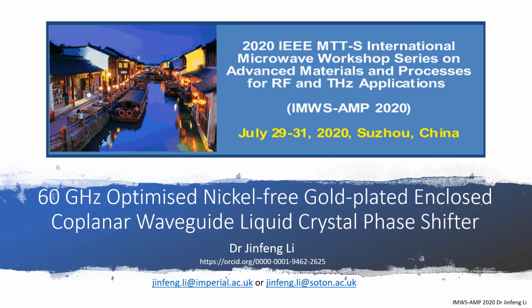In conclusion, this work numerically investigates and experimentally optimizes a novel nickel-free gold-plated ECPW LC phase shifter at 60 GHz. By comparative analysis of adaptive meshing inside metals versus the surface impedance models without meshing inside, we derived the threshold at which the conventional surface impedance model is invalid. This can be extended to a wide range of millimeter wave components, such as filters, antennas, and couplers, with the plating thickness comparable to the penetration depths.